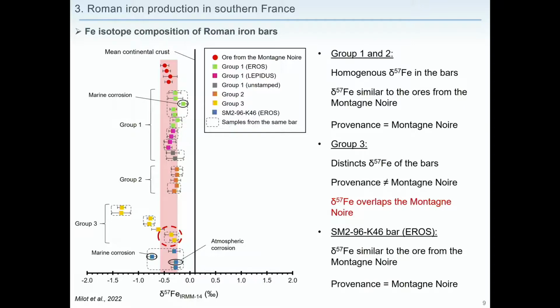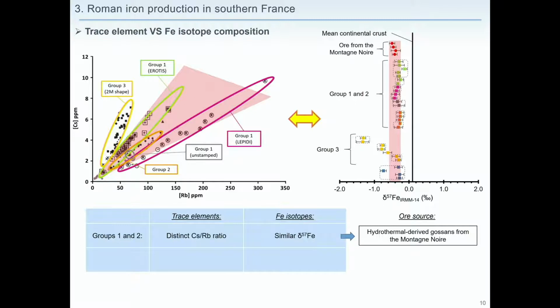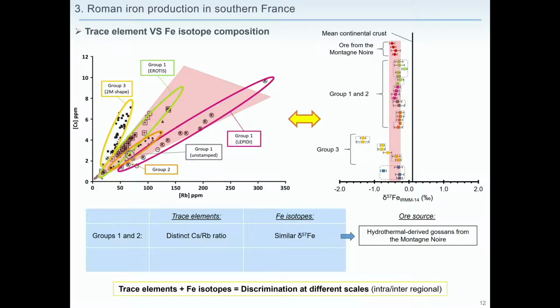So now if we compare these two tracing approaches, we have group 1 and 2 with distinct cesium to rubidium ratio and similar iron-isotope composition. So here we think this is inherited from the ore source of these bars, which are hydrothermal-derived gossans from the Montagne Noire. So if we only consider the trace element analysis, we can discriminate different workshops within the same region. And in contrast, the very narrow iron-isotope composition of these bars may allow discrimination in comparison with other regions of iron production, even if, unfortunately, we don't have an extensive database of iron-isotope composition in different regions of iron production. So, in fact, the combination of these two approaches allows discriminating at different scales.